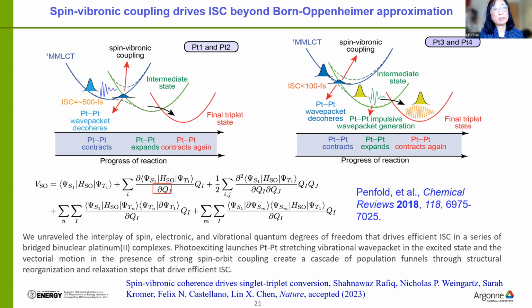The main point is that the APS study enabled us to look further, but then we also push forward to the faster time scale. The whole picture is that we can look at spin-orbit coupling, and that determines the intersystem crossing rate. But we cannot just look at the first term, the wave function overlap through the spin-orbit coupling Hamiltonian. There is also another structural factor that needs to be included.